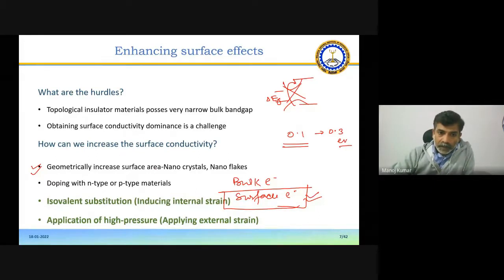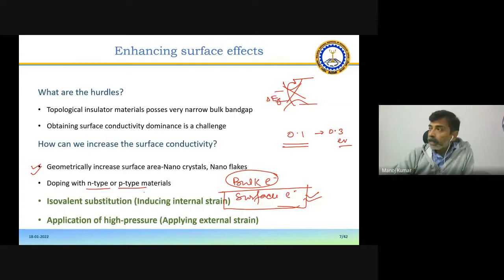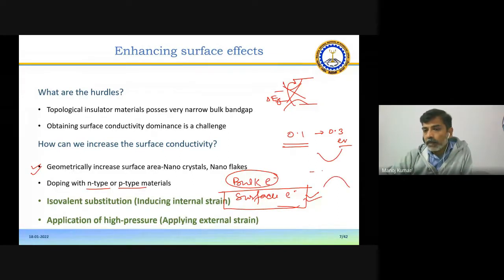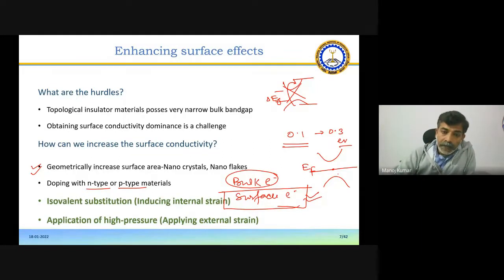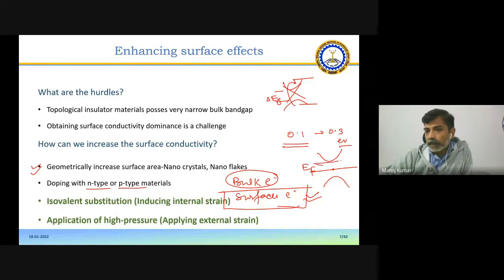We can also tune the bulk conduction by making it a compensated one. Making it compensated means making the Fermi level here at the center between the valence band and conduction band, so that the bulk conducts minimally. And we can directly do this by carrier doping. N-type doping or P-type doping, I think you are familiar with. So we can directly dope some additional electrons or holes into the material and tune it. To make it n-type, we dope the material where the EF goes close to the conduction band. For p-type, the EF goes close to the valence band. So we can do this type of doping.